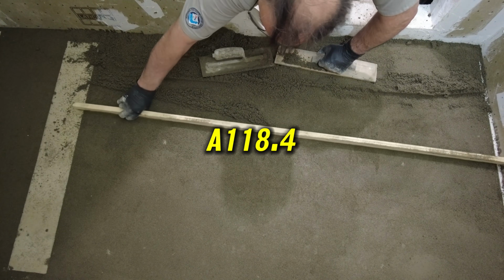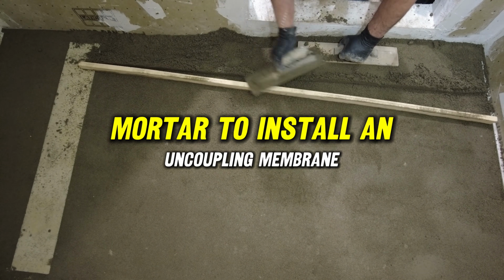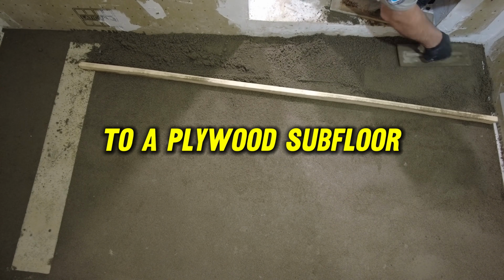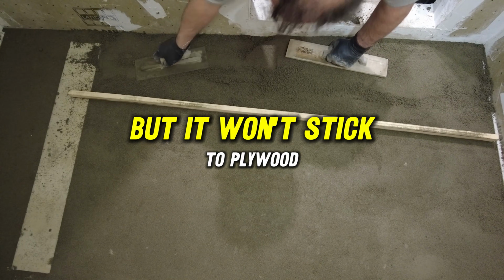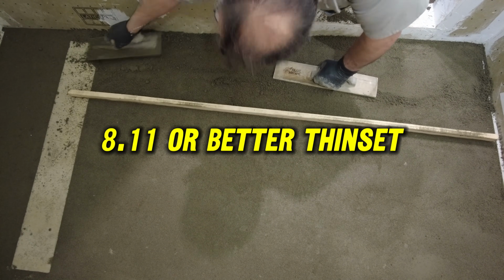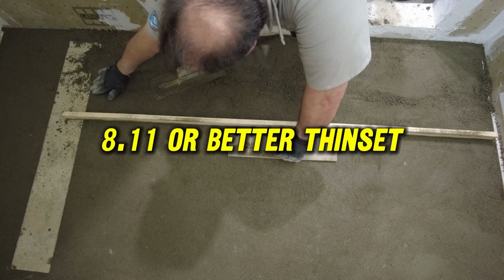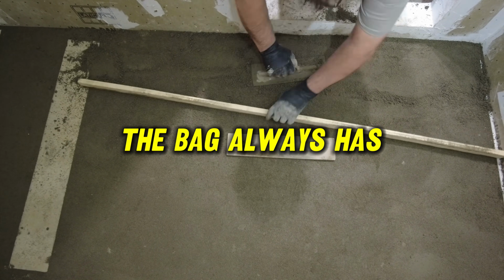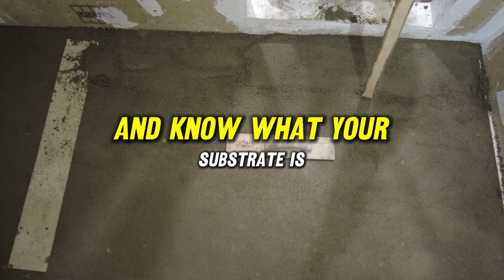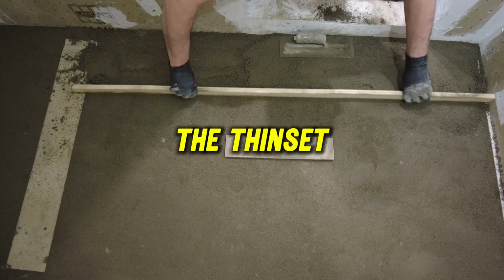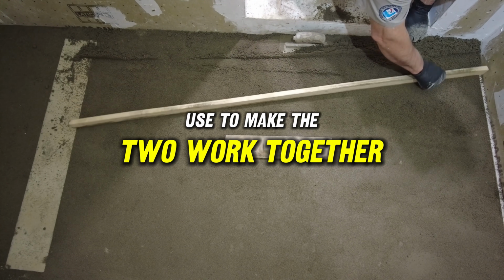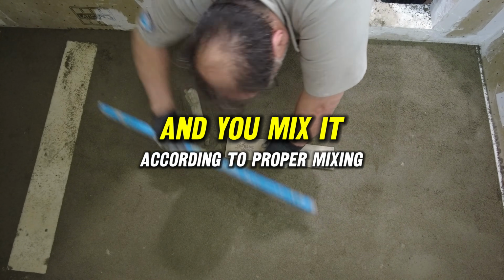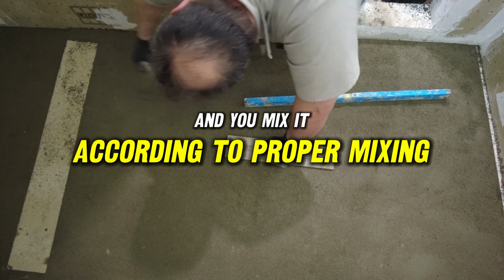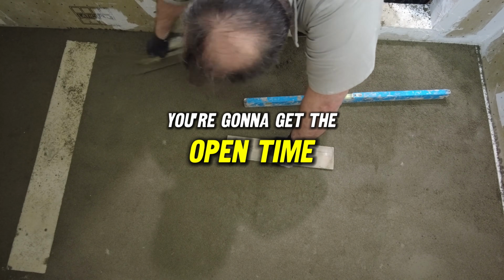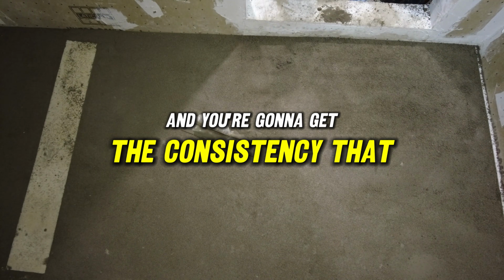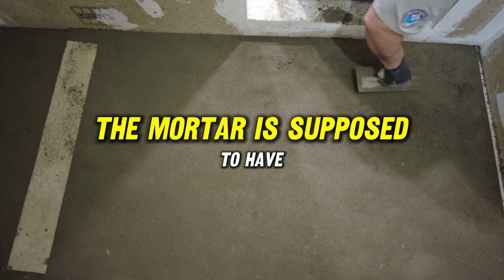If you use an A118.4 mortar to install an uncoupling membrane to a plywood subfloor, thinset will stick to the membrane, but it won't stick to the plywood. You have to use an A118.11 or better thinset. The bag always has the standard. Know what your tile is and know what your substrate is and know what the thinset you need to use to make the two work together. If you do that and you mix it according to proper mixing directions, you're going to get the pot life, you're going to get the open time, and you're going to get the consistency that the mortar is supposed to have.